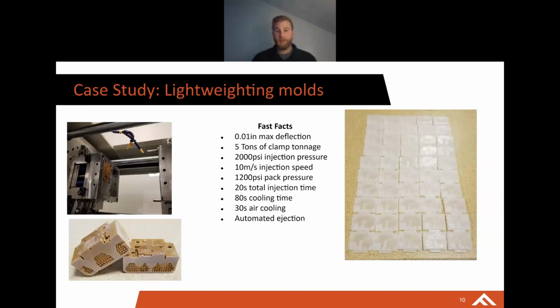But this test really showed that lightweighting our tools made no impact on the performance. We were able to reduce print time, reduce material cost, and run the exact same process with nearly the same results. This is, however, a great time to introduce the Fortify molding process. We're able to use really low clamp tonnages because of our material's ability to compress together. So we generally print slightly proud of our mold frame there, so that we can really squeeze those blocks together and get a nice parting line seal. So we're only using 5 tons of clamp tonnage for this.